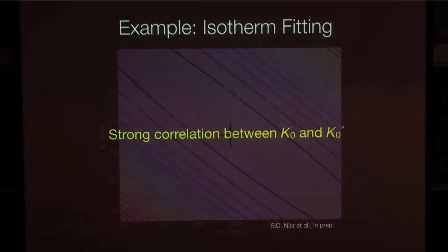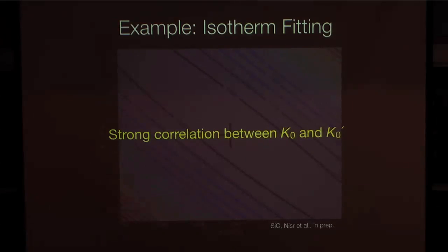The trade-off between the parameters really matters, because if you look at some tables to decide which value to use, and you see a negative correlation in pairs of values from 2 different groups, you think, oh, they are really different. But they may not necessarily be different in terms of the real data. They might be exactly the same, but the trade-off gives you a different pair of values.